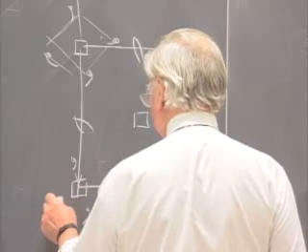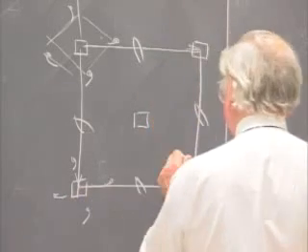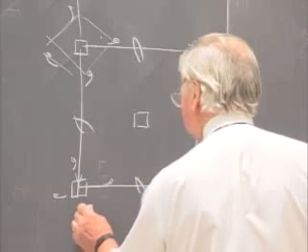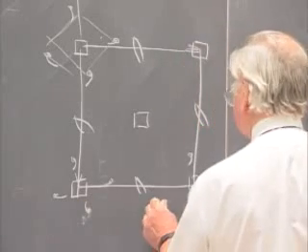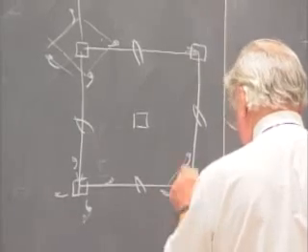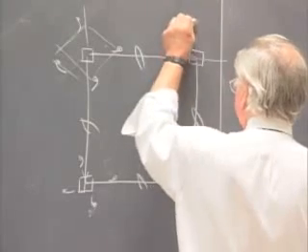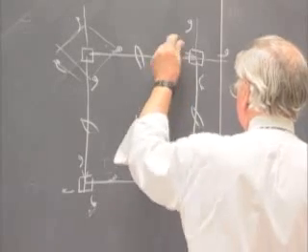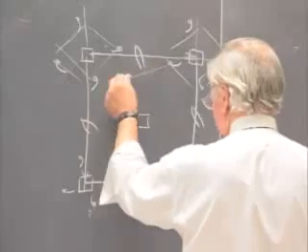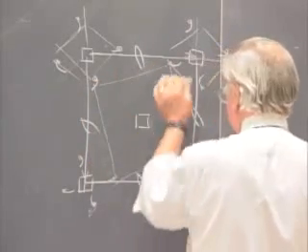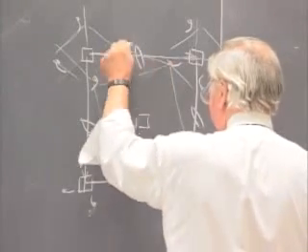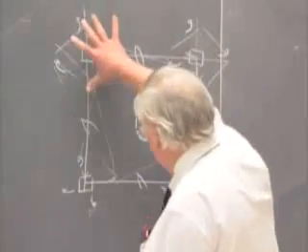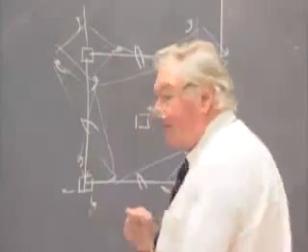Again, it's just the pattern of a fourfold axis that is hung at every lattice point of the square net. And these other symmetry elements that arise simply are things that relate the squares that are hanging at every corner of the square cell. Okay, so the square in the center of the cell, for example, relates these 4. And you can pick any other 4 and they'd be related as well. The twofold axis relates this to this. This twofold axis relates this to this, and this to this. So the pattern is just the square produced by 4 stamped out at every corner of the square net. And that's that simple.